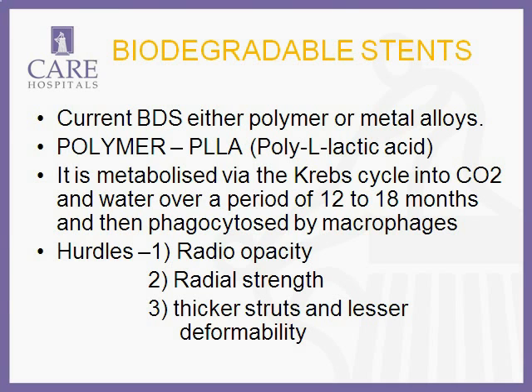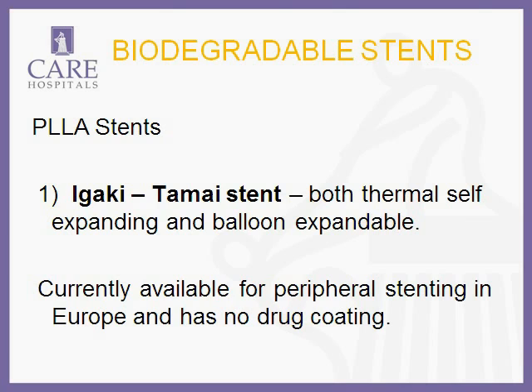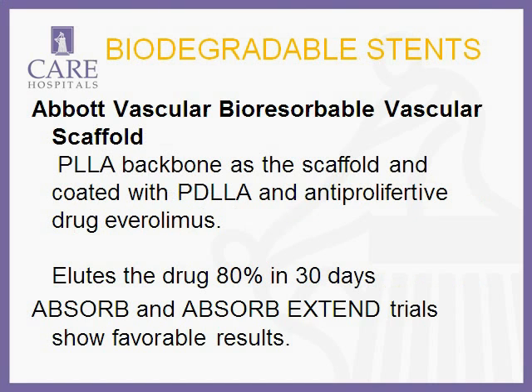In the trial there have been strut fractures in the patients where the stent was implanted, and the struts are slightly thicker and less deformable, so deliverability is an issue. Now the PLLA stent is the Igaki stent, which is now being used more for peripheral stenting, because for delivery you need to heat the stent, and this has been shown to cause damage to the endothelium.